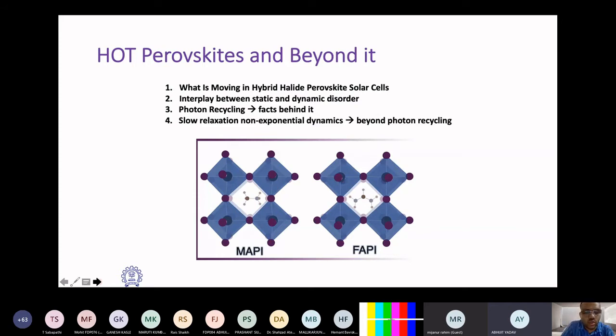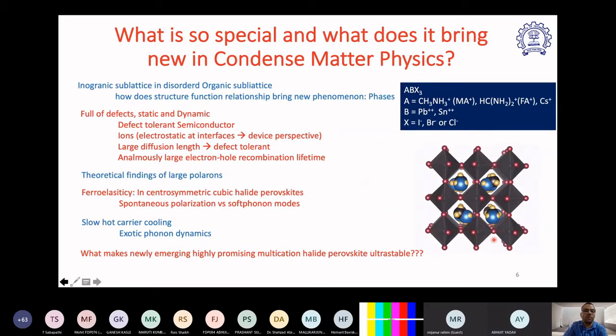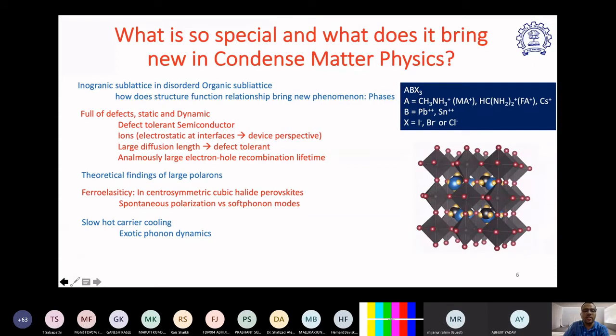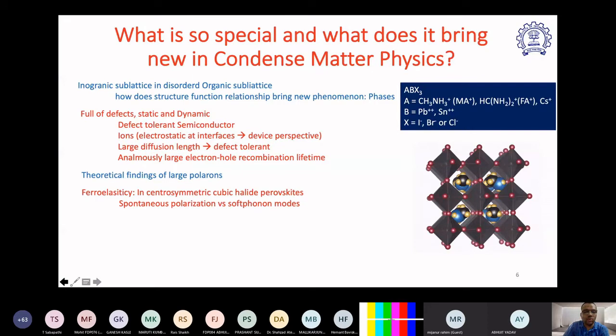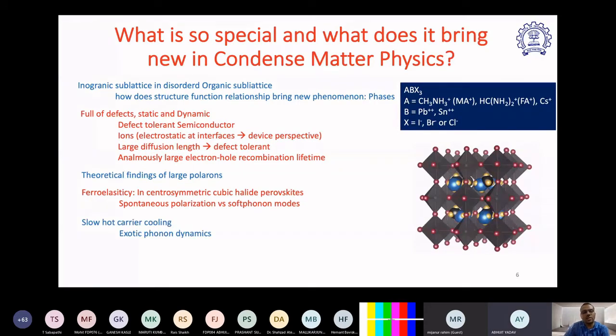So I was telling, so far I was talking about the methyl ammonium lead iodide or the formamidinium lead iodide based systems. However, we can have systems with a mixture of MA and FA as well. That will make the mixed cation, multi-cation halide perovskite, and those are the ones which are ultra stable as compared to the single cation. Because if you put your solar cell in the sun, and your semiconductor color goes back from black to yellow, the larger energy band gap color, then that means your solar cell material is not stable, and that can happen.